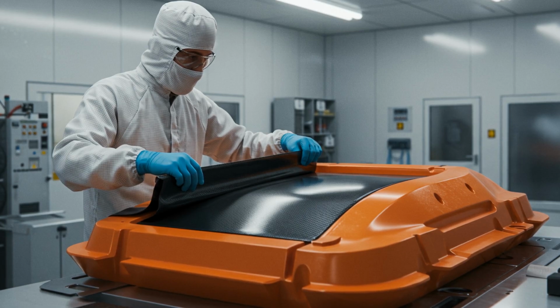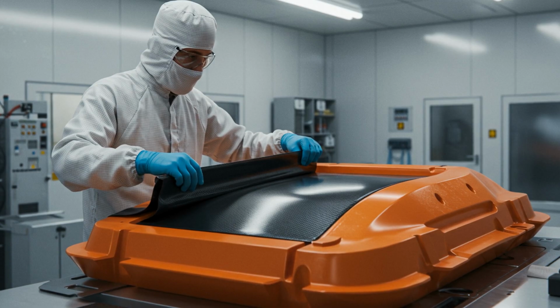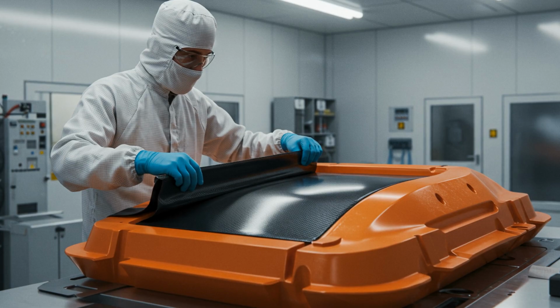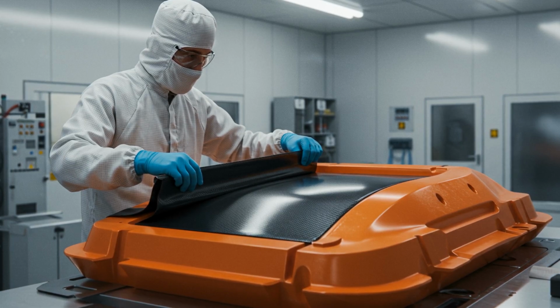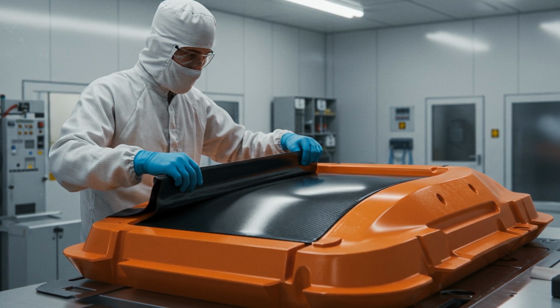As each layer is added, a technician uses a small tool to debulk the material, pressing out any trapped air bubbles. A single air pocket, even the size of a grain of rice, could create a weak point that leads to a catastrophic failure at 200 miles per hour. This process takes weeks of continuous, meticulous hand labor.